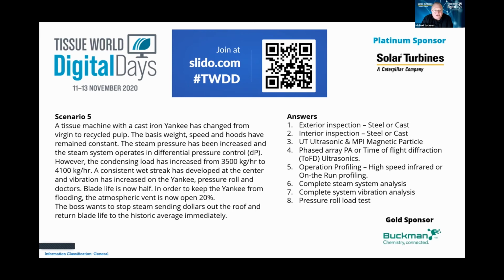Here we go, number 5. A tissue machine with a cast iron Yankee has changed from virgin to recycled pulp. The base weight, the speed, and the hoods, though, have remained constant. The steam pressure's been increased, and the steam system operates in a differential pressure control. However, the condensing load has increased from 3,500 kilograms per hour to 4,100. There's a consistent wet streak developing on the center, and vibration has increased on the Yankee, the pressure roll, and doctors. Your blade life is now half, so in order to keep the Yankee from flooding, the atmospheric vent is now opened 20%. The boss clearly wants to stop sending steam dollars out of the roof and return the blade life to its historic average. And guess what? He wants it immediately. Your answer, please. Choose from number 1 through to number 8.